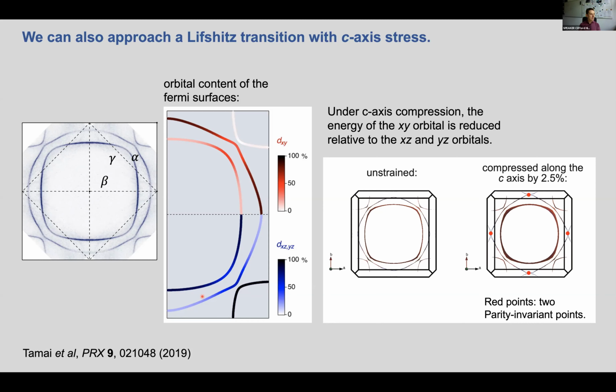For 20 years, the dominant hypothesis for strontium ruthenate was that it was an odd parity superconductor, a chiral superconductor with px plus i py order. Now in weak coupling calculations, you tend to find D wave and P wave superconductors quite close in energy. So as pure speculation, maybe under this strong c-axis pressure we do have a transition to odd parity order, and then an odd parity order parameter would not be favored by tuning to these Lifshitz points. That's very strange, though. You would expect it to tip in favor of something that could take advantage of this very strong density of states.